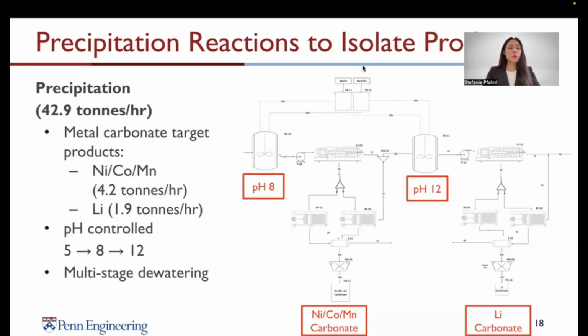So once we've reached this point, we finally have a stream that is composed only of water and metal ions, and we're able to extract out those critical metals. We do this in two pH-controlled steps, where we bring up the pH from 5 to 8, react the stream with sodium carbonate so that we create a nickel, cobalt, and manganese carbonate solid, and filter that out. That filtrate is then taken up to a pH of 12, reacted again with sodium carbonate so that we can get a lithium carbonate solid, and that is filtered out as well.